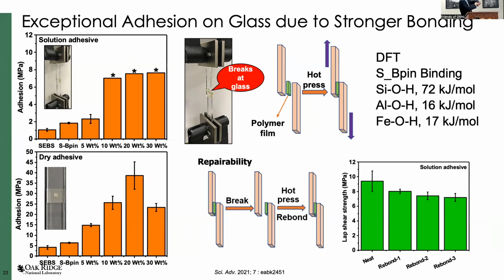Another thing is that you can recycle it. Even if you stick it, if you apply heat, you can take it off and put it on again. What you're seeing here is the starting material, do it again, do it again, do it again. You can reuse it. Most of our glues right now you cannot reuse. You just stick it, done. It's pretty difficult to reuse. Because of the chemistry, this is showing it. Also a little more detail: this is the calculation of interaction energy. Glass is silicon hydroxide, with the oxide group on there, so that is higher than aluminum or iron. That's what's shown there.